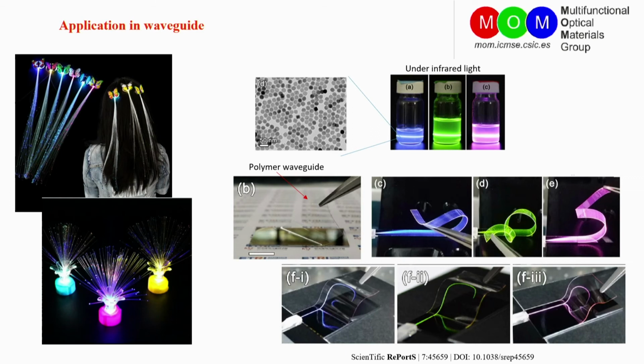The phosphor particles can be applied to prepare waveguides as well. They are dissolved in a polymer to obtain highly viscous solutions. And by printing the solutions, polymer waveguides can be obtained. They are very stable. They emit strongly under bending and rolling conditions.